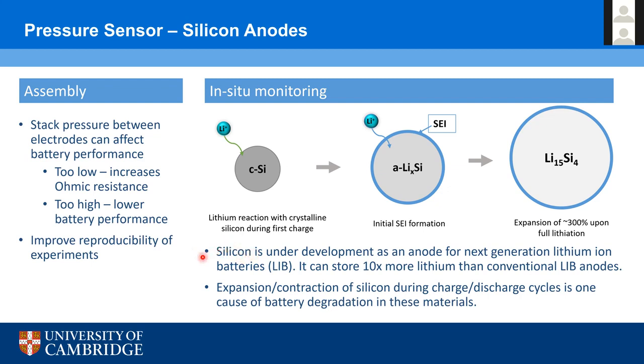These are interesting materials because they can store 10 times more lithium, 10 times more energy than conventional lithium-ion batteries. The reaction occurs as follows: you start with crystalline silicon, and as you lithiate the silicon, you go through these amorphous phases, eventually getting to the crystalline Li15Si4 phase, where the silicon is expanded by around 300%.